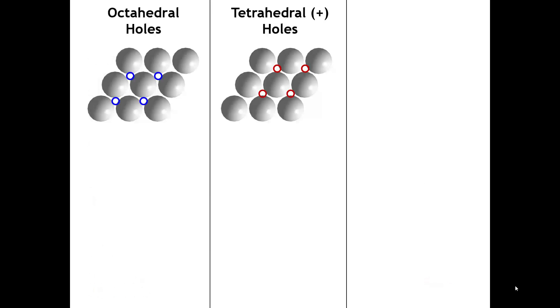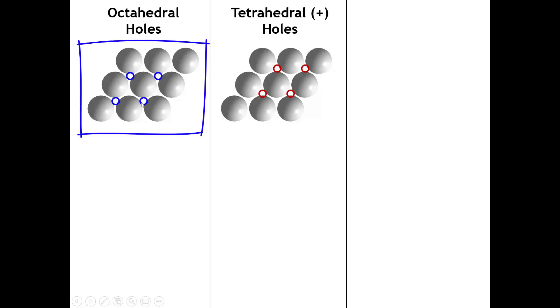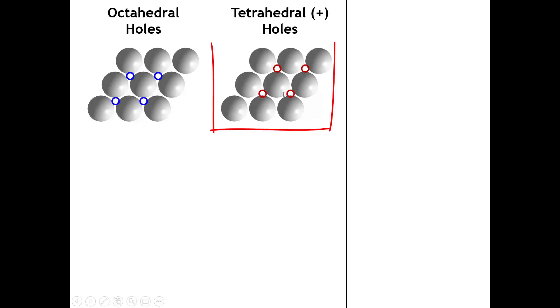Let's take a closer look at these holes. Here's a small snippet of a close-packed layer—let's say it's anions. We could describe these structures as a close-packed array of cations with anions in the holes, but conventionally that's not what we do. If we put cations into the blue set of voids on top of the layer, each cation is nestled against three anions below, making a triangle. Adding another layer above provides three more anions in a triangle pointing the opposite direction.